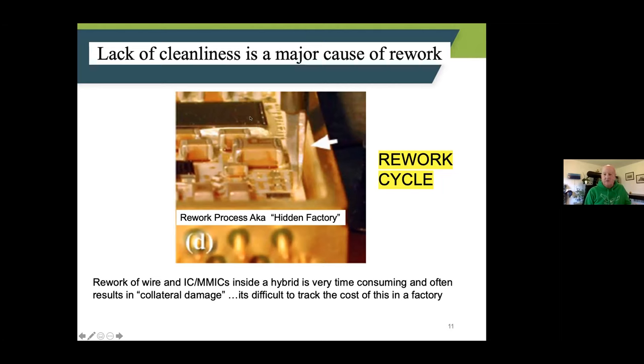You've got to get above the glass transition temperature of the epoxy, get in there with a tool and dig it out. When that happens, you may shatter the chip, you've got loose pieces of wire, and you've got all that residual silver epoxy that has to get scraped out. And when you do that, it's called collateral damage. You have little bits of foreign material that go all over the place, and you've got to clean those out. And then you have to carefully dab down another little squirt of epoxy, place it down manually, and probably go offline to some older manual equipment and try to, well, first cure it.